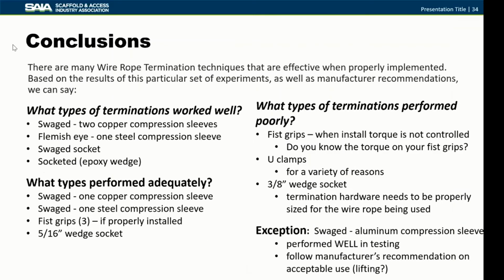So our conclusions after looking at all these different types of terminations. Number one is that what we found is that there are many effective types of terminations when they are properly implemented. So from this, again, my disclaimer at the beginning, this was not a scientific study, but from this limited evaluation that we did, what types of terminations did we see that worked extremely well? Well, swedged with 2 copper compression sleeves, a Flemish eye, done as I described earlier with the back weaving and 1 steel compression sleeve, the Wedge Socket, and the Spelter Socket with an epoxy wedge. All those worked extremely well and provided strengths that were greater than the catalog strength of the wire rope.